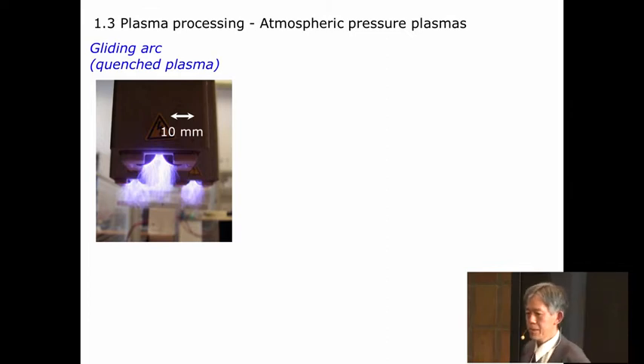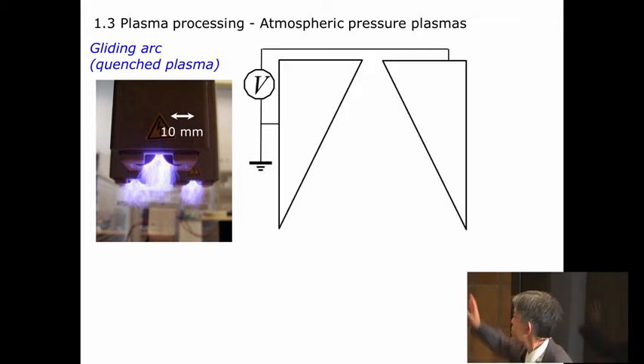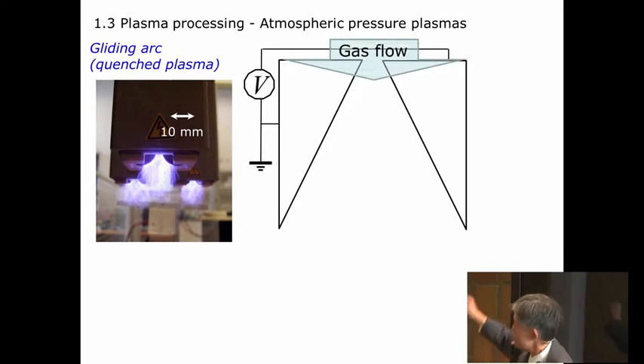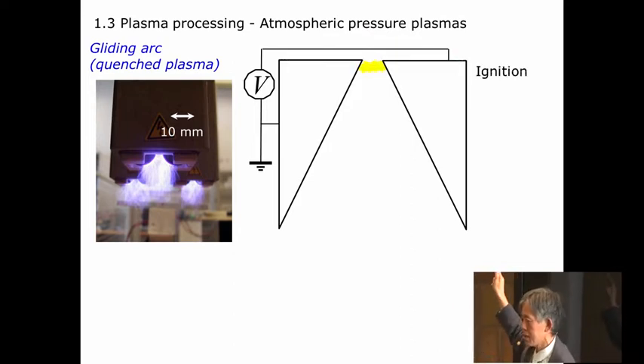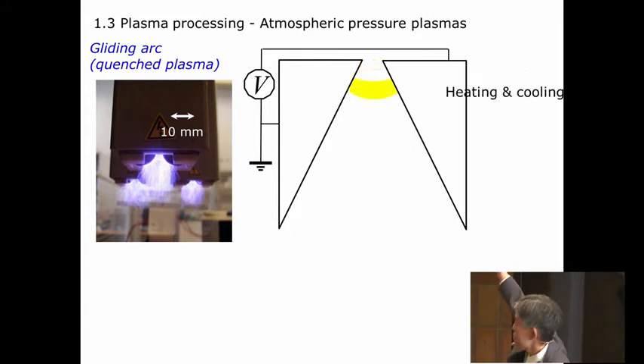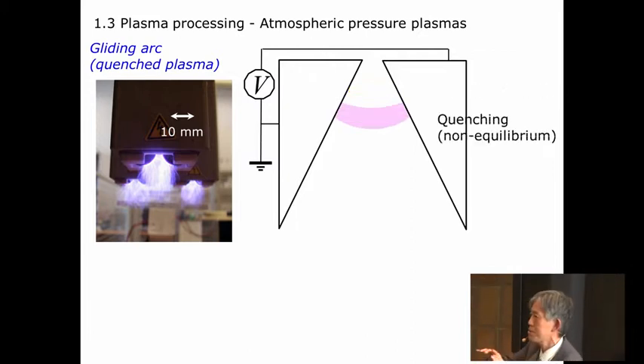Then the next one is the gliding arc. Gliding arc has a very long history. It was used since the 19th century, if I understand correctly, and there are a lot of nice applications from that. But you typically need two diverging electrodes applying voltage between them, having gas flow, then there's the ignition, then it becomes immediately an arc. So you are already in the arc stage, but the plasma is extended by gas flow and heating by the voltage, but cooled by the gas flow. Then at some point, because of the increase of the surface area, cooling overcomes heating. Then it becomes non-thermal, non-equilibrium condition. That's quite nice.